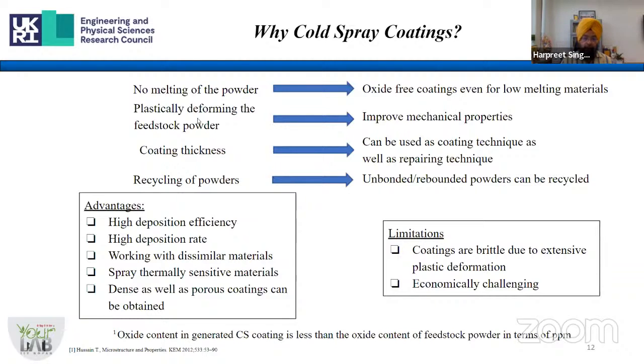coatings. Another thing is that it plastically deforms the feedstock powder, like a severe plastic deformation process. And in that, we have seen that there is a kind of grain refinement also happening. There are studies where we have seen dynamic recrystallization during this severe plastic deformation, and you can see the microstructures are quite impressive. And of course, if the microstructure is refined, you can expect better mechanical properties.